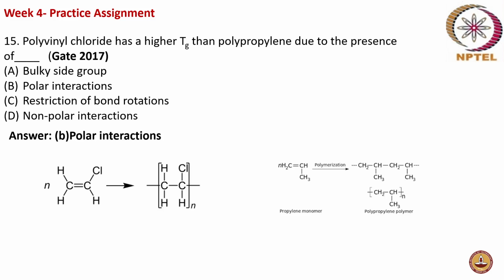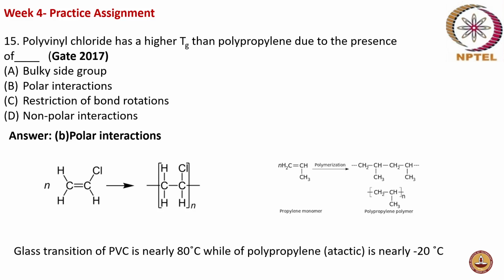Perfect. Polar interactions, as you said. The chloride group causes polarity. So this polar interaction makes polyvinyl chloride have higher glass transition than polypropylene, which has only a CH3 group. Okay. So the glass transition of PVC is nearly 80, while that of atactic polypropylene is nearly minus 20.